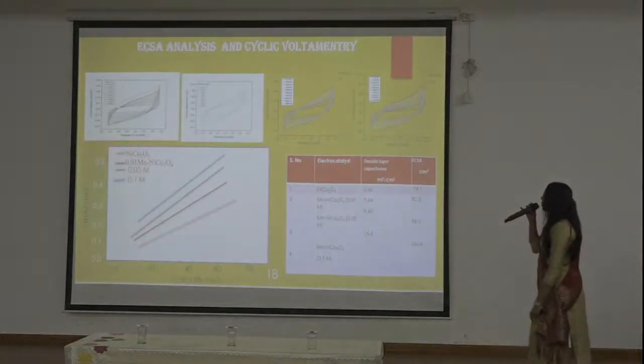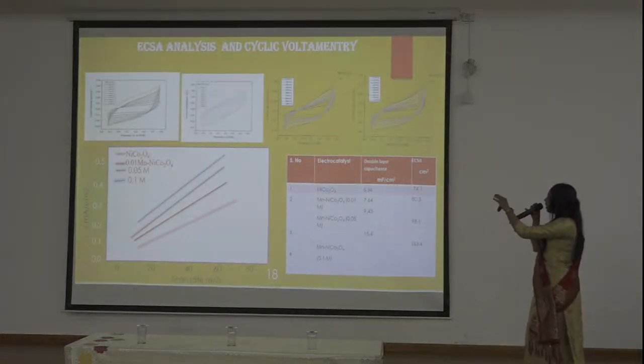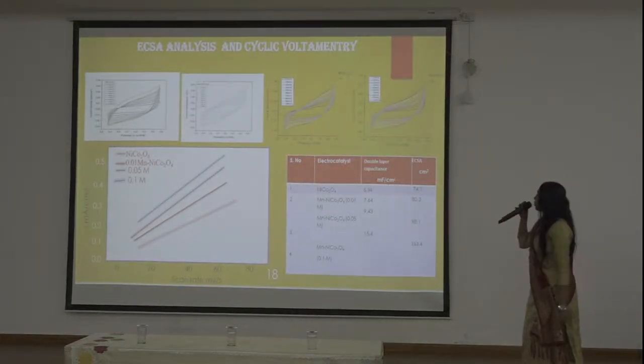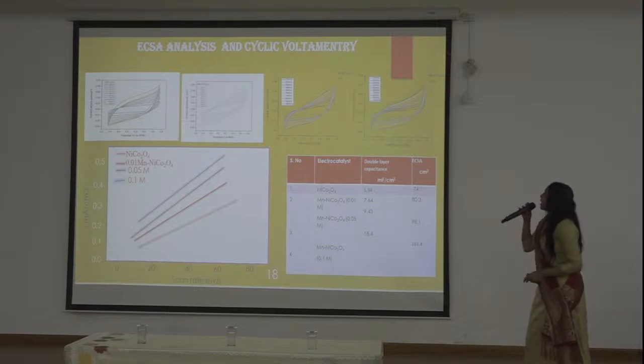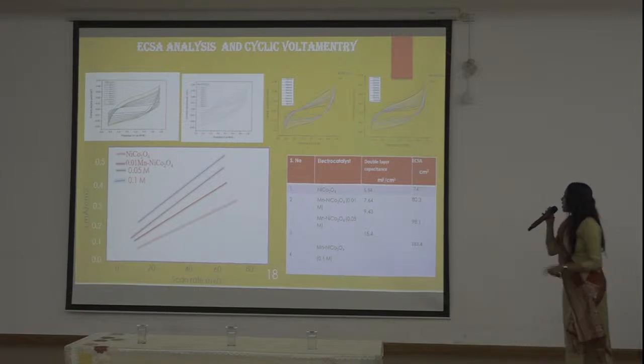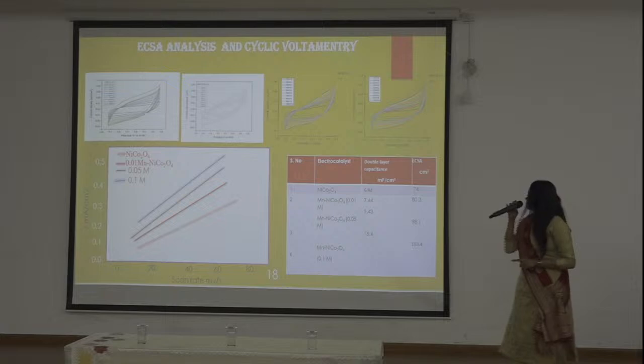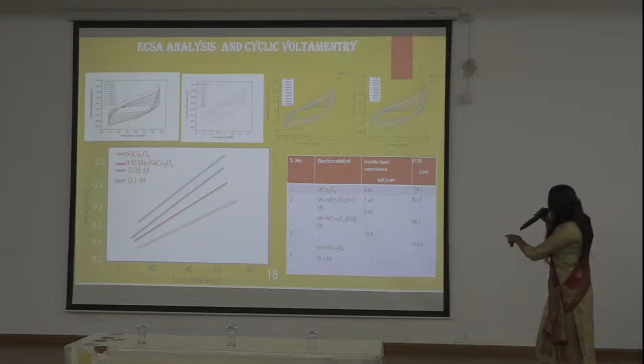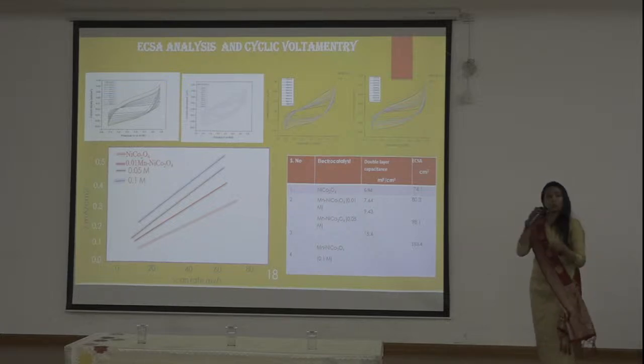Next slide. By using cyclic voltammetry, I have calculated electrochemical surface area, which I get good result in manganese doped nickel cobalt oxide 0.1 molarity ratio.